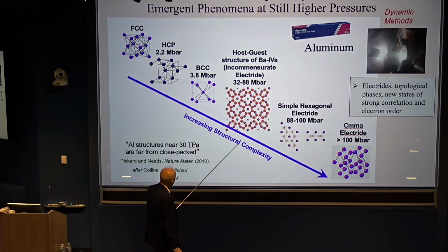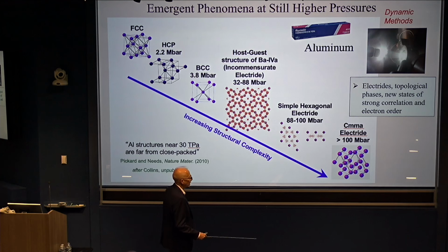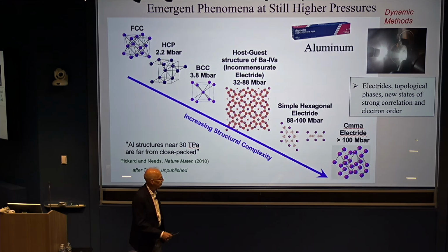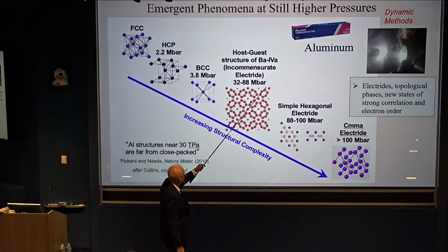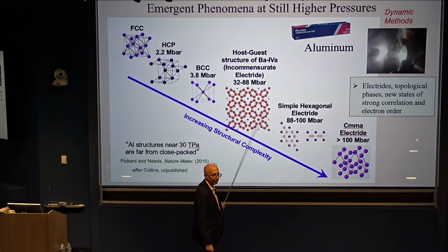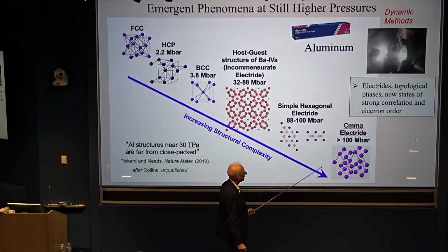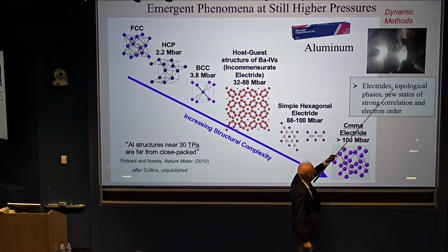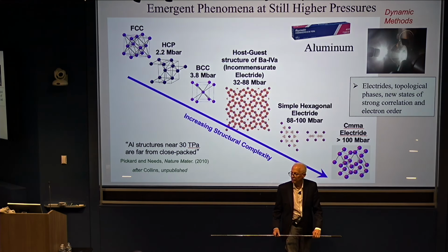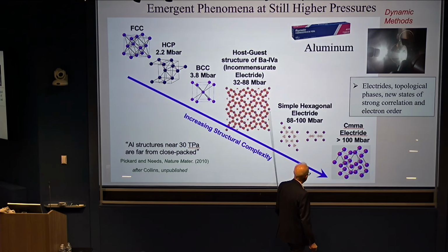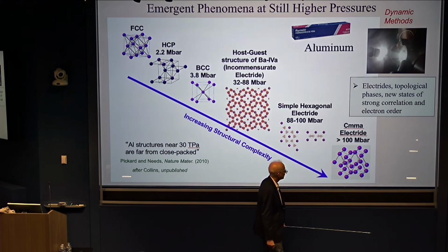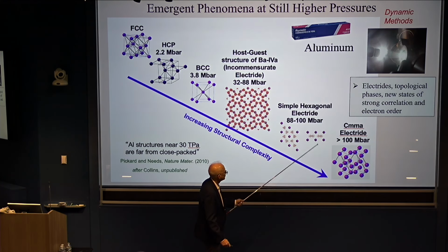And maybe one more example, going to still higher pressure, with more emergent phenomena, not necessarily superconductivity. I mentioned the electrides and the scrambling of electrons that occurs in sodium. We take other elements, for example simple aluminum foil, and compress it maybe up to 100 megabars. We expect to find very interesting structures that are reminiscent of a type of chemistry occurring at extraordinarily high pressures. This is far beyond what we can do with a diamond anvil cell. We have to use dynamic compression techniques like those at the National Ignition Facility, but this is a regime that's ripe for the study of new topological materials and other states of order, of correlations in electronic order, that might ultimately be useful.